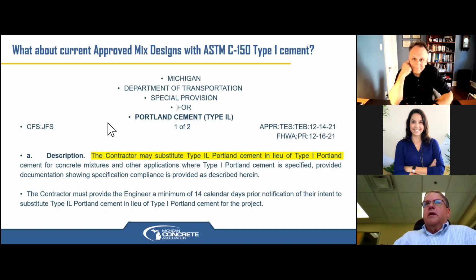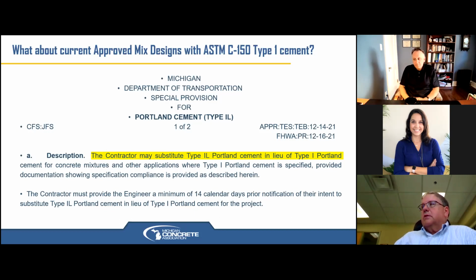We had to face reality. How are we going to handle the mixes that are out there? Most mixes that MDOT has are good for 2 years. There are projects that are continuing. So we put this special provision together, worked closely with John Staten at MDOT and Tim Stallard. But the bottom line is this special provision is out there. It can be incorporated in jobs from either the 2012 spec book or the 2020 spec book. It basically says contractors may substitute type 1L cement in lieu of type 1.